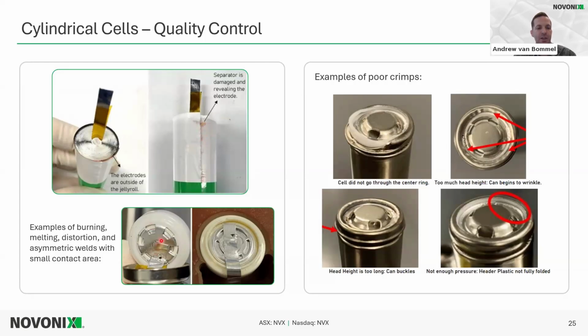We have to ensure that during that laser welding process, there's no distortion of that weld or asymmetric welds with a small contact area. It has to be good contact, and we can check that by that hole test.